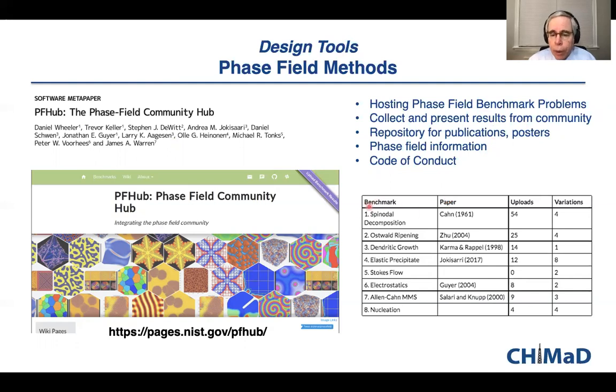And so, for example, spinodal decomposition is one benchmark, and we've had 54 uploads and 4 variations of the problem suggested. Same with elastic precipitates, for example, 12 uploads and 8 variations. And this has been very helpful for not only understanding existing codes, but it's been also helpful for the community to develop new ones. And one example of this is Sandia National Labs is developing a phase field code, and by using this phase field community hub, they were able to get their code running faster and in a more accurate way than they would have otherwise.